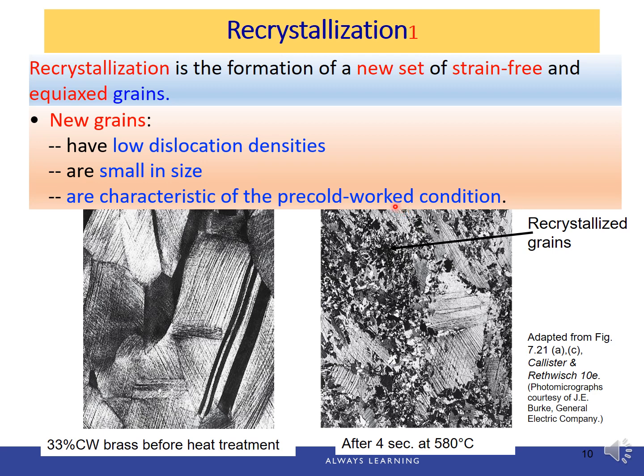And the driving force to produce this new grain structure is the difference in internal energy between the strained and unstrained material. So the new grains form as very small nuclei and grow until they completely consume the parent material, which is a process involving short-range diffusion.